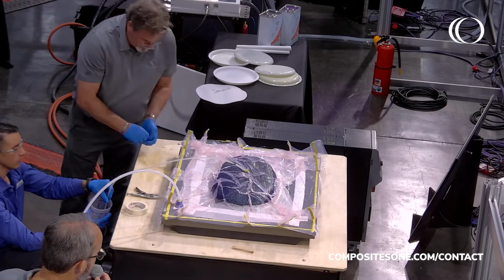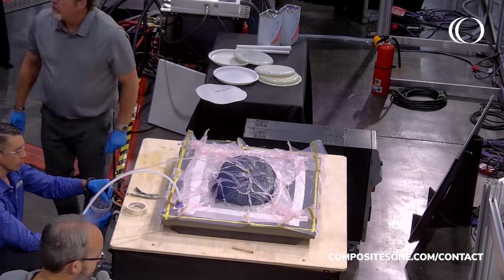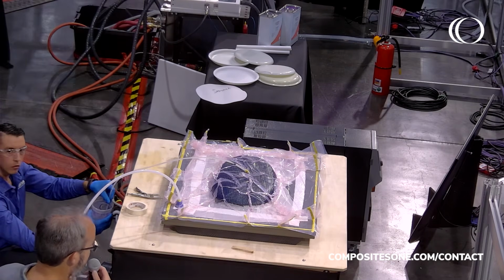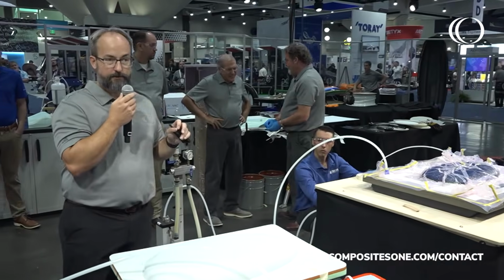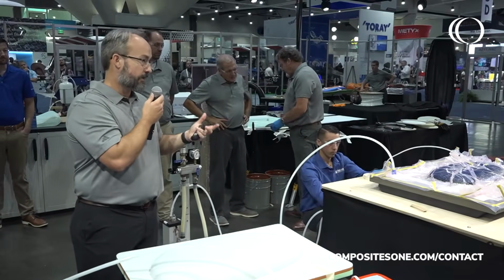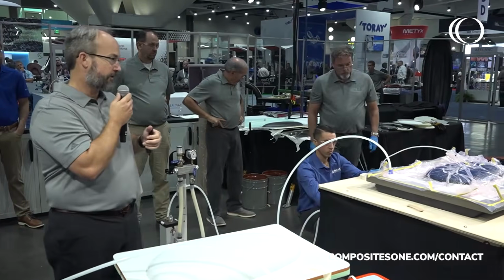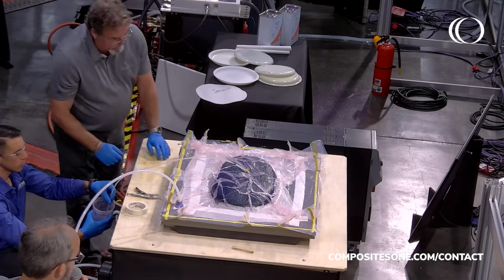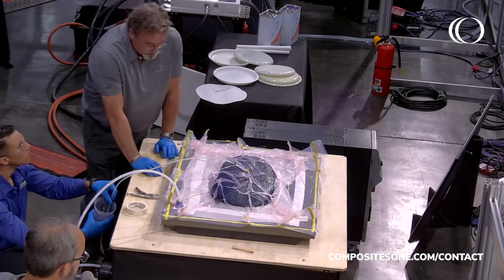So after the infusion, we can ramp the temperature up even further, have the resin gel, and we could even post-cure it on the mold, and then cool it back down to our demold temperature.